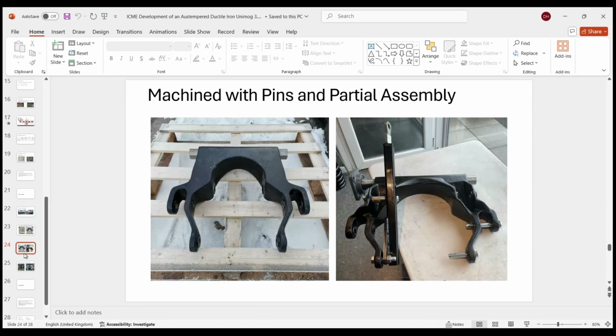So now we can see a part assembly of the component, and you can see the hydraulic arm there, and now you can see it's on that sort of vertical, and obviously there's no angles for it to seize in. If the arms were initially at an angle, as that arm was lifted up and down, it would seize, and actually that arm had enough force to bend those arms, and then obviously again it would cause a problem with operational use. Yeah.